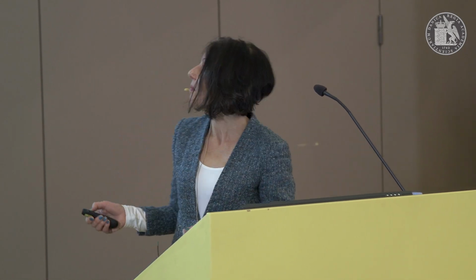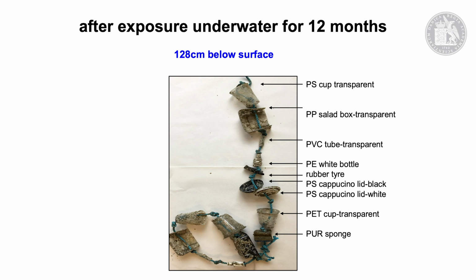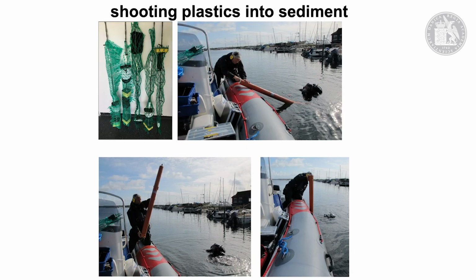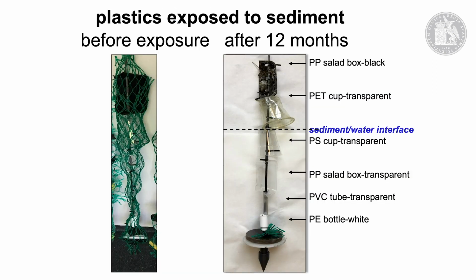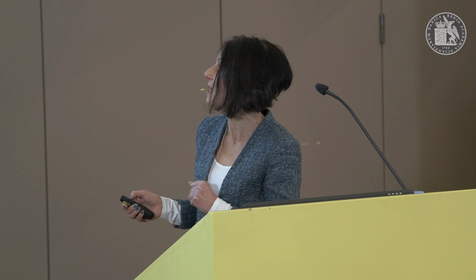We have all the different kinds here. Polystyrene cup that was transparent, black polypropylene salad boxes, polyurethane sponge, cappuccino lids. The samples that were shot into the sediment have also produced interesting results, because after the same period of time, the ones that were actually in the sediment show nearly no degradation. They look totally new. But the ones that were just stuck up, it was quite a difficult process to have these down so deep in hard sediment, they have a little bit of growth.